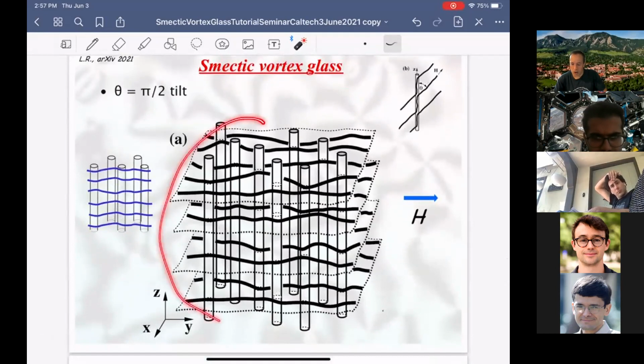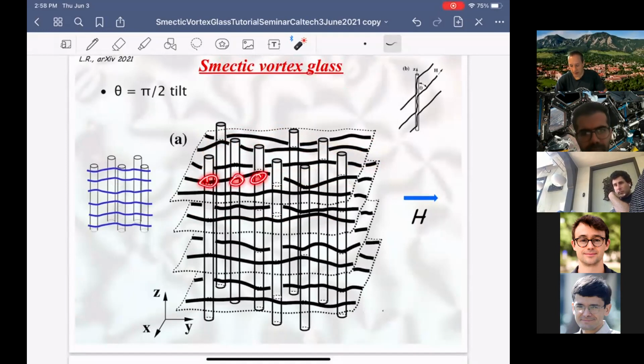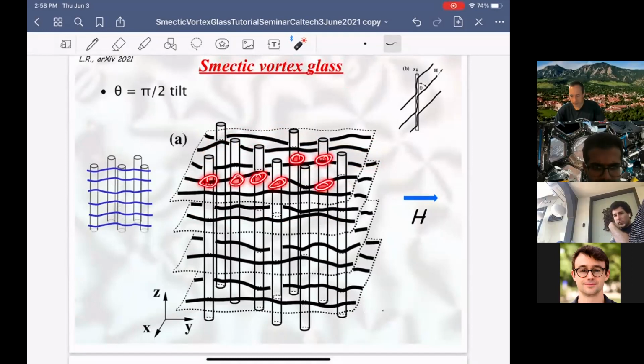Well, here's the picture of it. So here's my three-dimensional picture. Here's the columnar defect. So I'll call that the z-axis, the columnar defect. Magnetic field now is applied perpendicular to it along the y-axis. And then there's, of course, the x-axis. So you sort of have planes. You have flux lines that are running like this in sheets. And what do they really see? What they see are cross-sections of these columnar defects, point disorder for the distortions in the x direction. And these columns, let's assume they're z independent. So there's no randomness in the z direction.